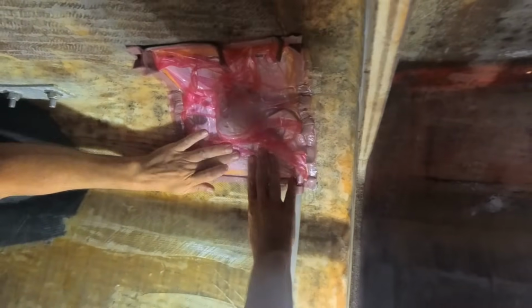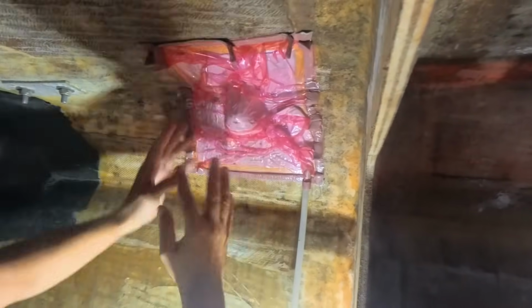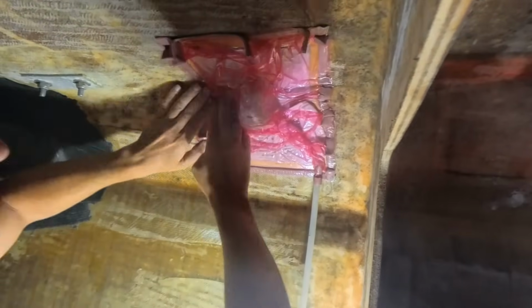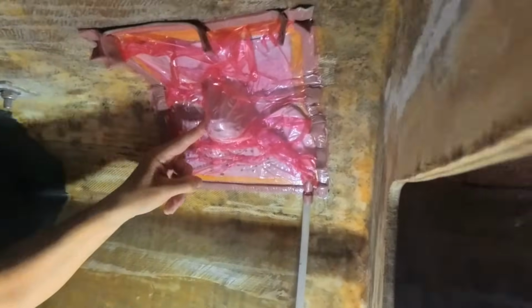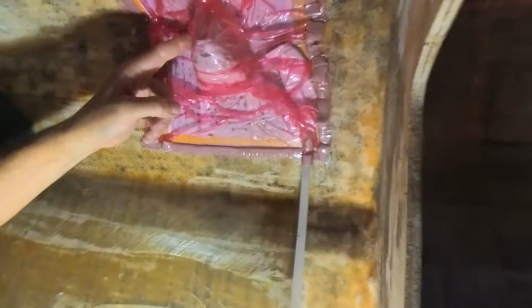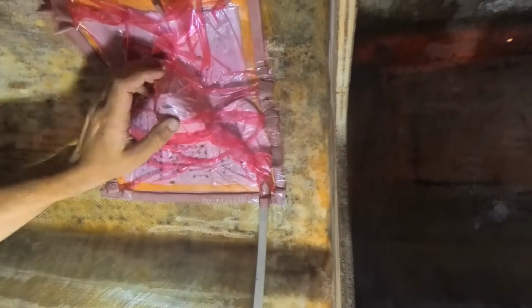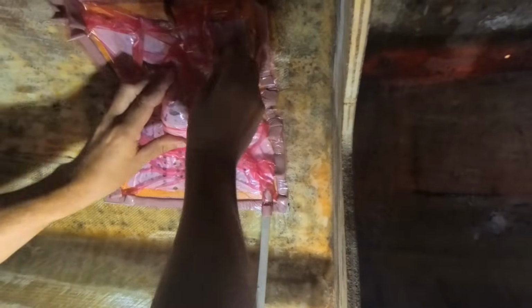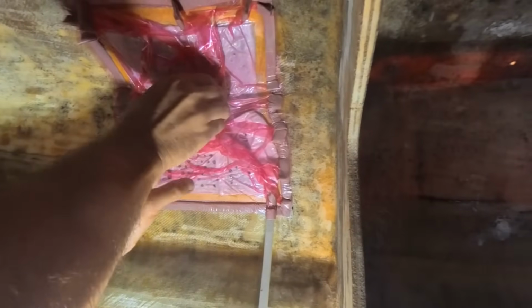Now, when I'm setting my bag up here, I want my bag to be a bit leaky, so you can see I can manipulate the bag while I don't have a huge amount of vacuum on here. The main really big thing I'm focusing on is making sure that I push in these internal corners so that I don't have bridging. Bridging is your worst enemy in a vacuum bag, because that means the vacuum bag is not pushing the laminate down in and onto your job.